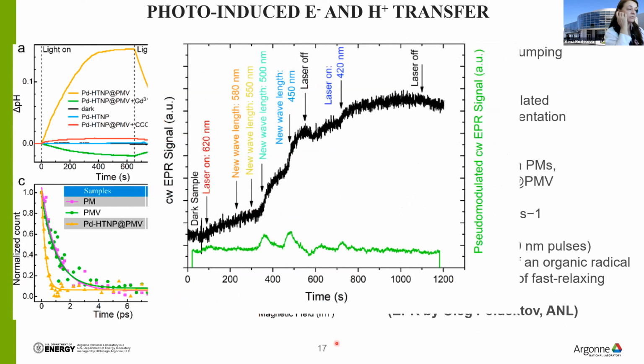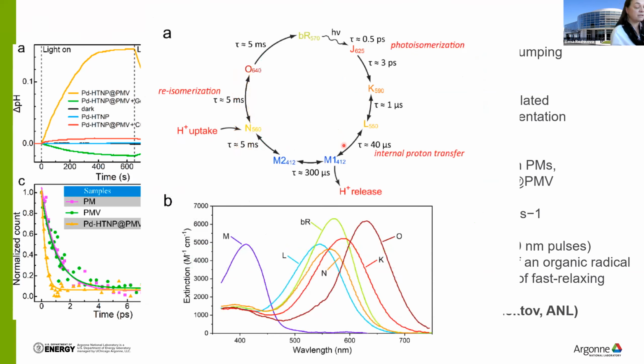And even more interesting, Oleg tried different laser wavelengths to see what kind of wavelengths were more efficient to produce this charge separation state. And it was observed the most efficient charge separation was at 450 nanometers and 500 nanometers wavelengths of light. And it's interesting if I show you the photocycle of the proton pump. At these wavelengths, around 400 and 500 nanometers, it's exactly the step when the proton is released and transferred across the membrane.